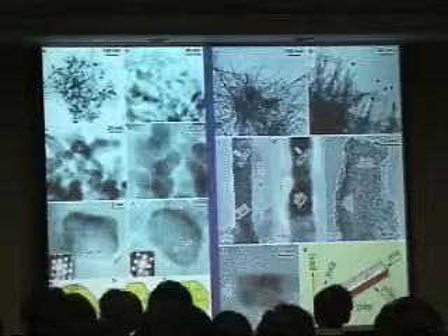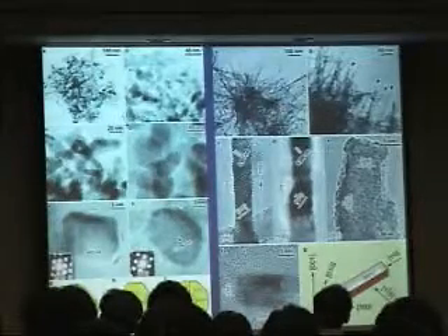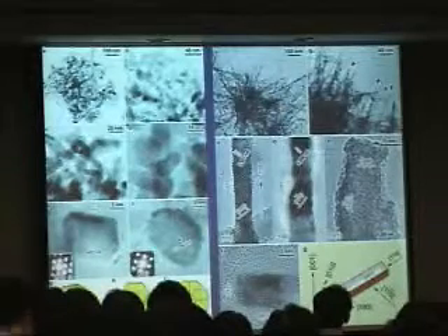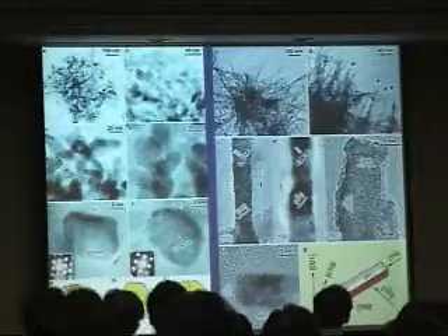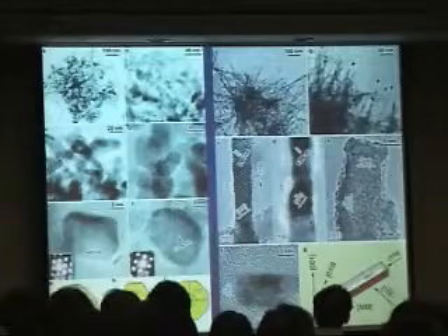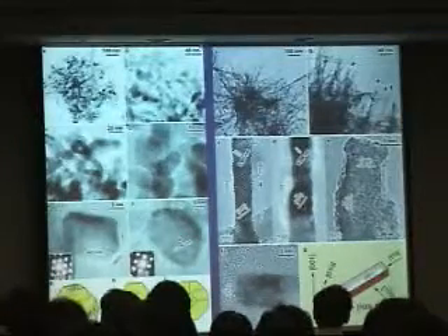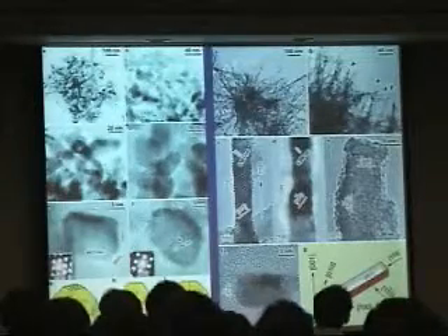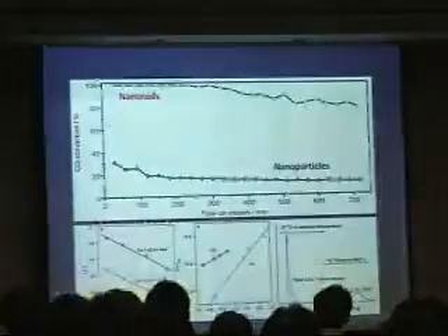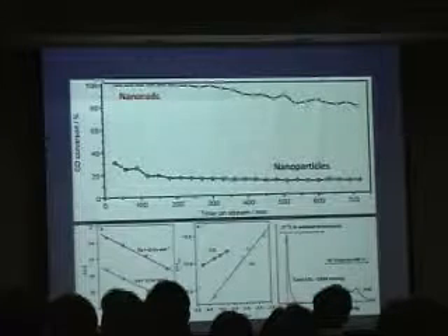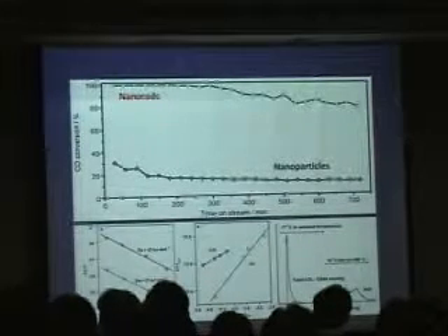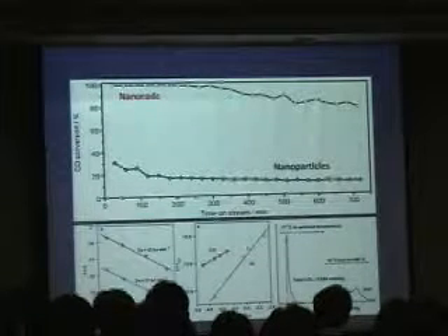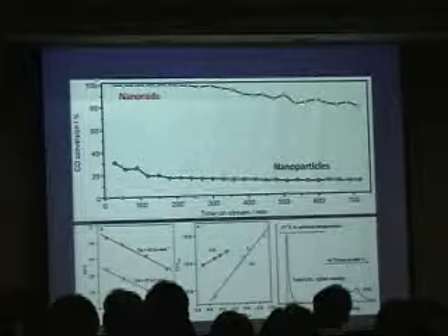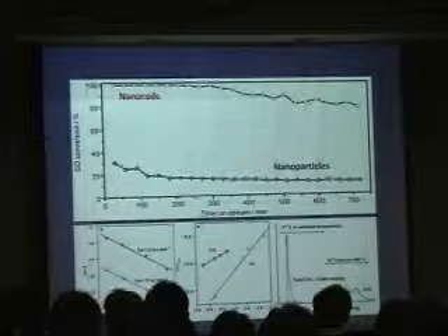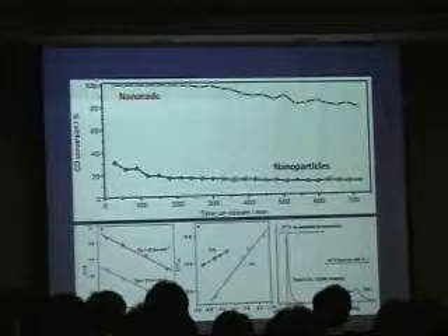And if we start from the rod-shaped precursor followed by thermal calcination, we get this type of cobalt oxide rods. If we also have a very detailed analysis of the crystal surface of those rod-shaped oxides, we find that it mainly exposes the 111 surface, of course, but also on the narrow side, there is a newly exposed crystal facet, that is the 110 surface. And we used these two samples for CO oxidation under the same reaction conditions. We find that their performance is largely different. The difference can be as high as 10 times. That means the nanorods are very highly active, and the nanoparticles, the spherical particles, show the normal performance as reported in many articles previously.